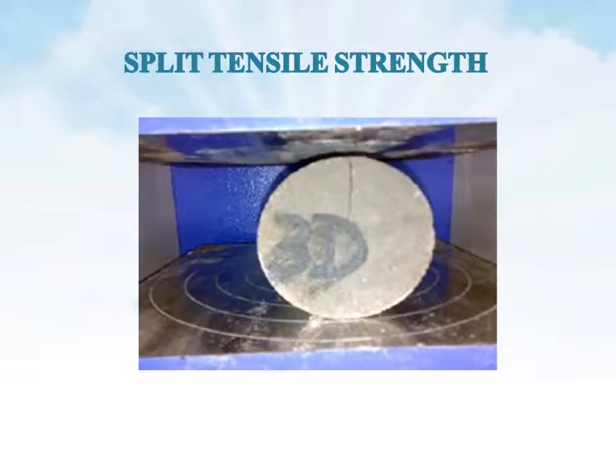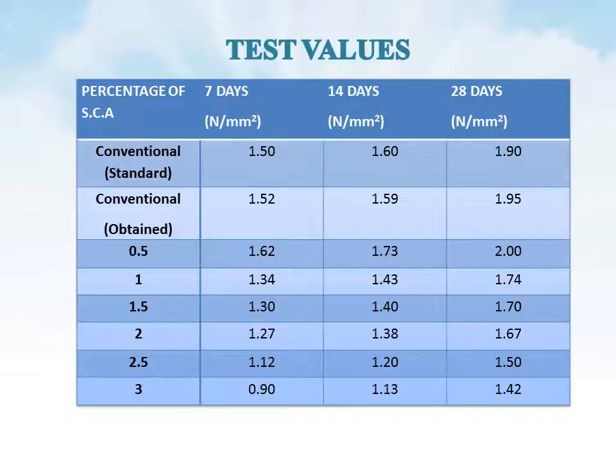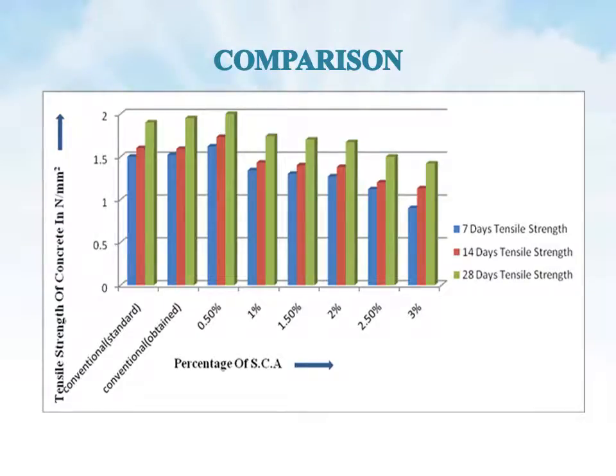Split tensile strength. It's an indirect method of measuring tensile strength. We conducted split tensile strength tests in the concrete lab for 7 days, 14 days and 28 days, using concrete cylinders. From these also we got the optimum value at 0.5% of self-curing agent: 7 days 1.62 Newton per mm square, 14 days 1.73 Newton per mm square, 28 days 2 Newton per mm square. This is a comparison chart of split tensile strength of conventional and self-curing concrete.